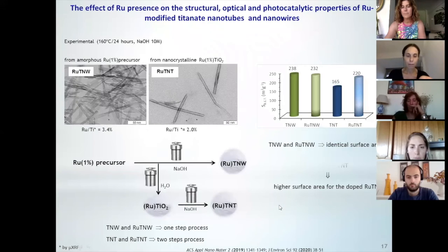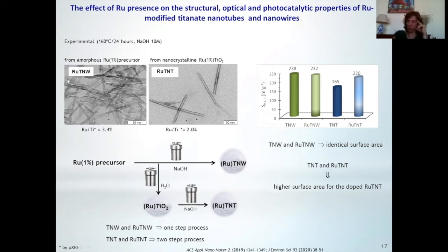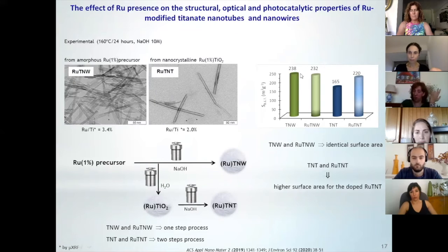Then we decided to see the BET surface area, and look. Under these conditions, as I told you before, the morphology of these nanoparticles is very stable. So we have almost the same surface area. That is not true when we look at the titanate nanotubes. We have a lower value when we try to prepare titanate nanotubes, and we also have a higher, but not so much higher, surface area when we have nanotubes. Why? Well, I don't know.